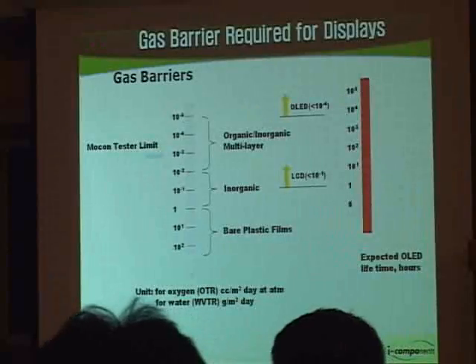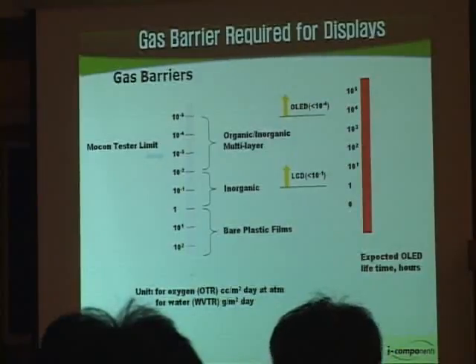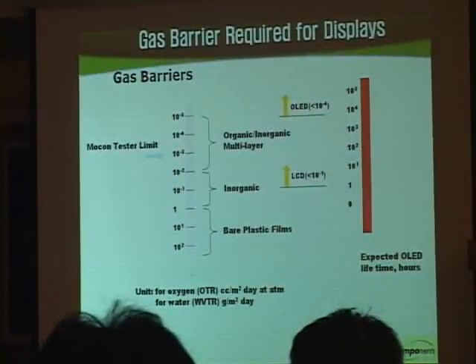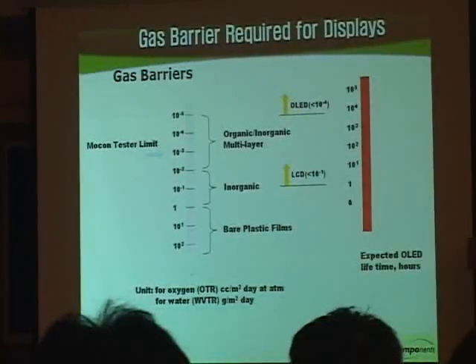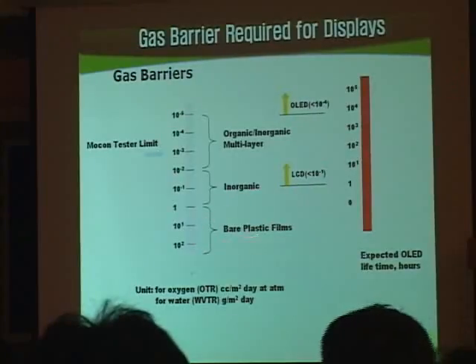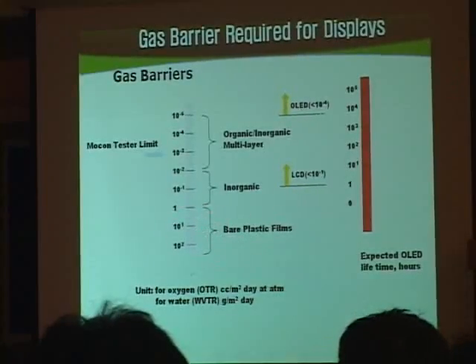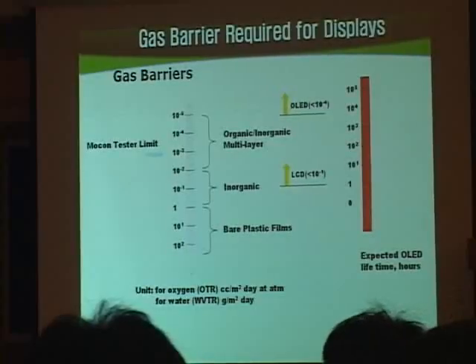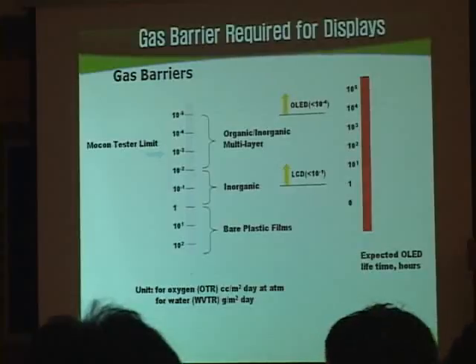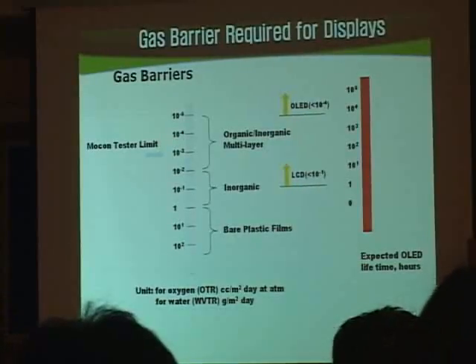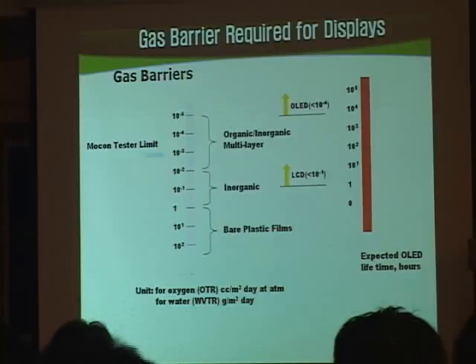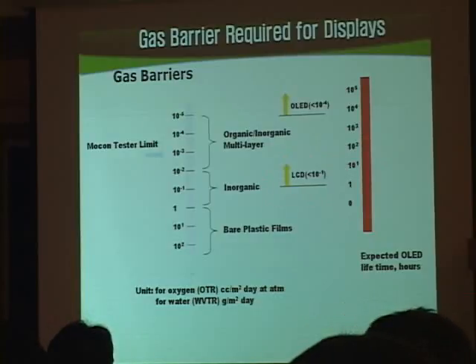Then comes the question of gas barriers. For the films used in flexible displays, all the time the very lacking property is a gas barrier property, since the plastic film usually has this kind of moisture barrier or oxygen barrier properties. However, for the LCDs, 10 to the minus 1, 10 to the minus 2 is required. And then for OLED, this morning it was pointed out that even 10 to the minus 6 is required to safeguard this display. So it's a very typical topic that we need to discuss, but since I'm focusing on LCD this time, I am at this range, rather easy to achieve, so I would not talk too much